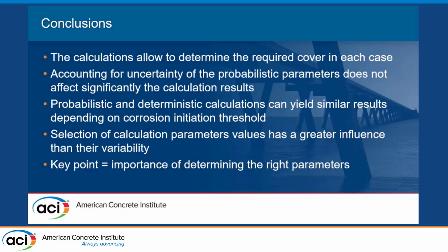So if we don't know the exact uncertainty about our transport parameters, we can use values that are documented from other projects, and we won't end up with a prediction that's totally false, or not in the right ballpark. So that's another finding that we had here.